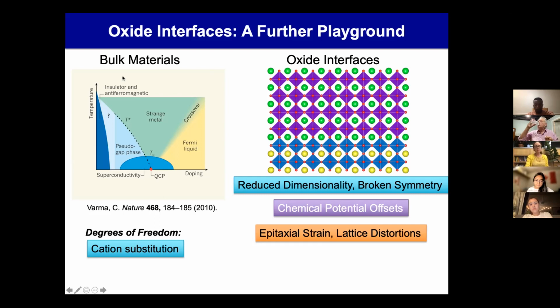If I took one of these bulk crystals, they're ceramics. If I took one of them and tried to pull on it and stretch it by 10%, it would just shatter. I mean, you would make much less than 1% changes before it would shatter. So in these thin film limits, you can really distort something and pull it apart, physically separating the atoms, which could very profoundly change how the spins on neighboring atoms overlap and interact with each other.